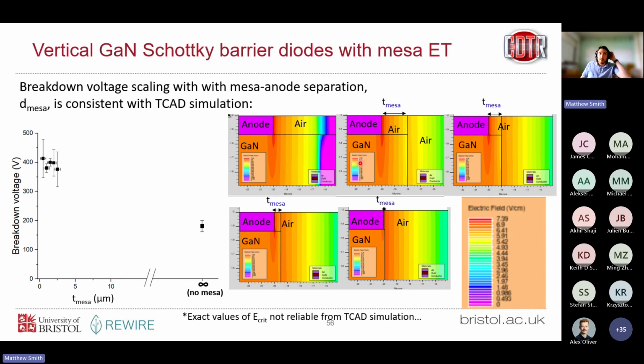Well, we can see from this series of structure files from Silvaco, this is the electric field at the anode edge here. So this is where the electric field peaks. And as we reduce this value T MESA, so again, as we make the MESA edge closer to our anode contact, we're suppressing this peak in the electric field close to the anode. So this is what we mean by edge termination.